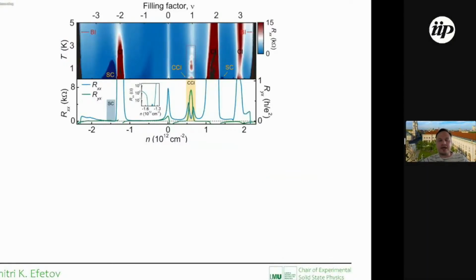And to give you some flavor of the richness of this material, and also to give you a little bit of a taste of the sort of measurements and phase diagrams that we obtain. Here is, I'd say it's not typical, but it's one of the nicer devices which were measured with transport in magic angle twisted bilayer graphene. And this really just shows you resistance. Here, one axis is resistance, the other axis is Hall voltage. So basically, this is the Hall resistance in a small magnetic field as a function of carrier density.